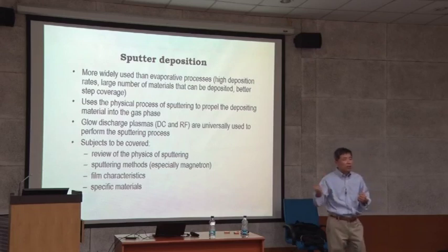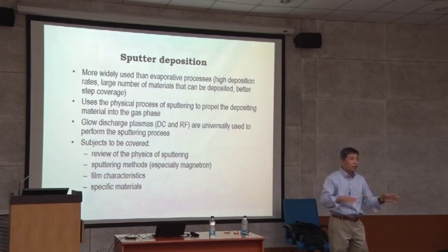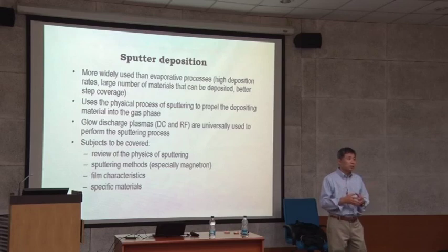And the nice thing about sputtering is that you cannot grow good nitride by evaporation, because molecular nitrogen is not very effective for reaction. This is a reactive process. You need an atomic nitrogen source to grow a nitride; for gallium nitride growth, they use cracking, like ammonia cracking. But sputtering is a plasma itself, and it dissociates nitrogen into ions and atomic nitrogen.